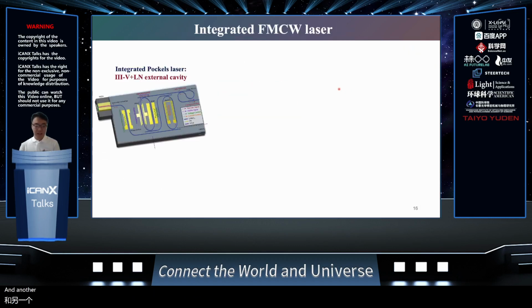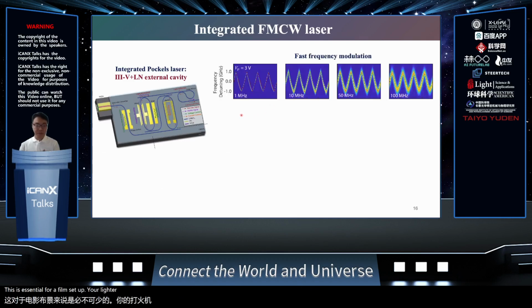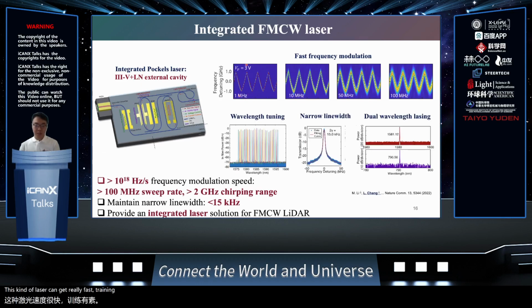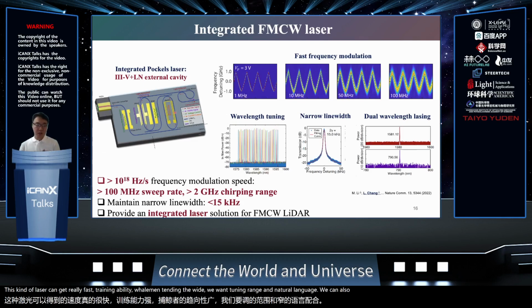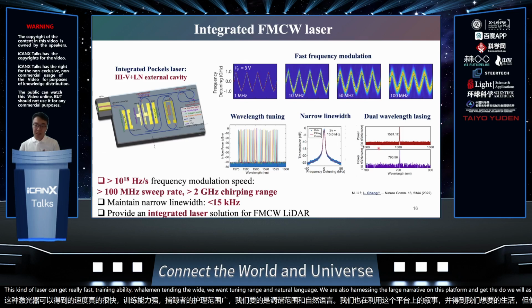Another important function previously missing in the integrated photonics world is fast frequency modulation capability. This is essential for FMCW LiDAR. Here, the strategy we use is to combine the lithium niobate-based external cavity with a III-V laser, which creates a new kind of laser. We call it a Pockels laser. This kind of laser can get a really fast tuning capability while maintaining the wide wavelength tuning range and the narrow linewidth. We can also harness the large nonlinearities on this platform and get dual wavelength lasing. This is the first dual wavelength laser for integrated photonics.